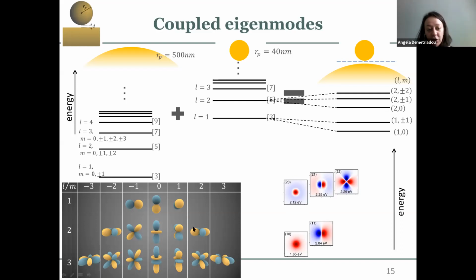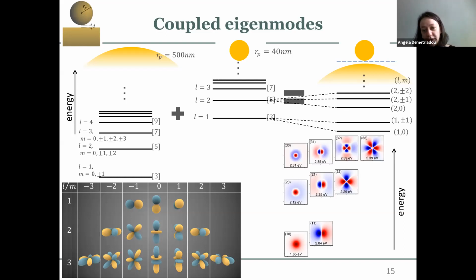And if you look carefully, they actually correspond to the profiles that you see for the spherical harmonics in this case here, which are disturbed a little bit by the very large nanoparticle. And so on, it keeps going on for the higher order modes. They all split their degeneracies. And here I'm plotting for the third order modes, where you have the 3,0, 3,1, 3,2 is the second order of this one. And then you have the 3,3 mode. And they're all confined in the gap because of the strong coupling, because of the tight coupling between the 2 systems here.